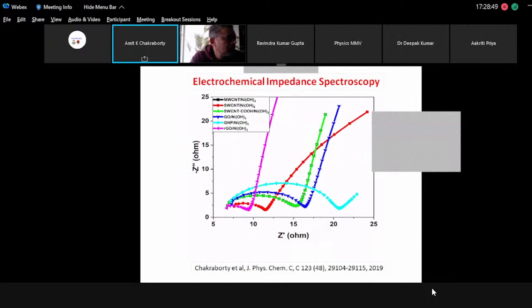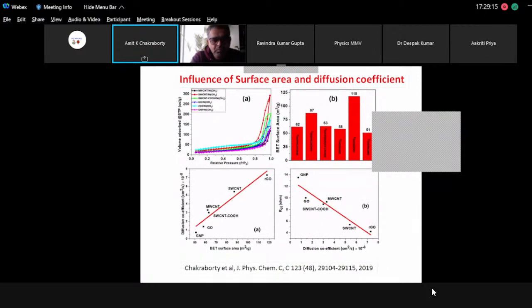Okay. So to understand the reason why RGO gives the best result, we tested this with EIS, and from EIS also we see that the RGO has the lowest radius for the semicircle. So that is the reason the charge transfer resistance is small for RGO. But is this all? Is the charge transfer resistance the main reason for the difference? To investigate that, we also compared the specific surface areas of all the structures, and we found that the specific surface area of the RGO composite is the highest. It is 118, and next to it is 87, which is for single wall carbon nanotubes. So we find that the specific capacitance is not purely dominated by the charge transfer resistance. Rather, it is a compound function of charge transfer resistance as well as the specific surface area.